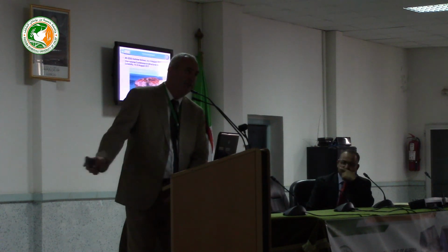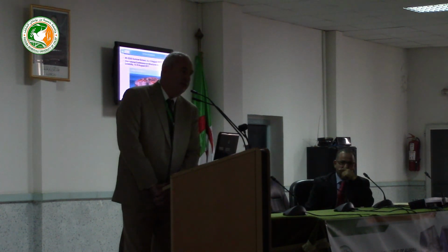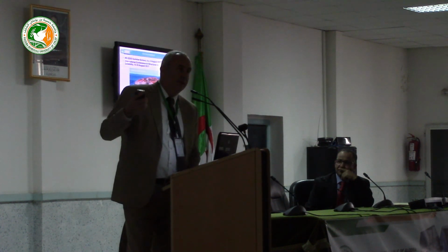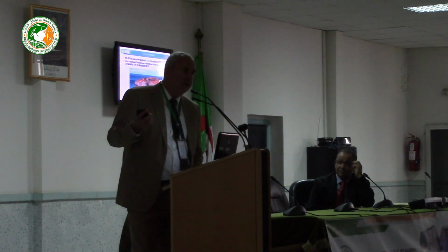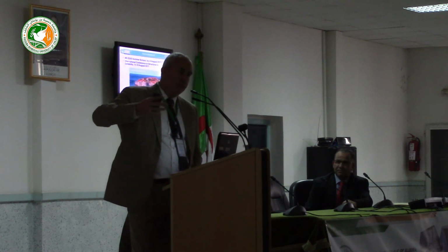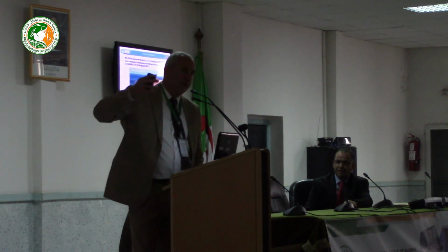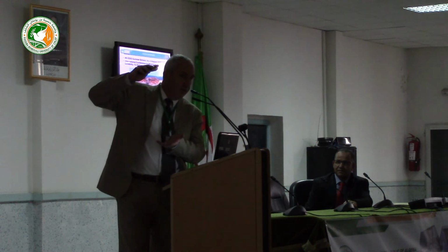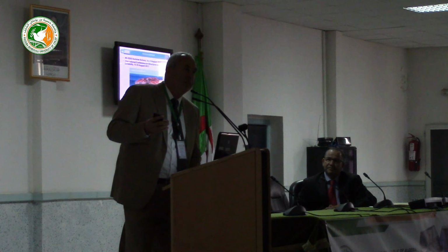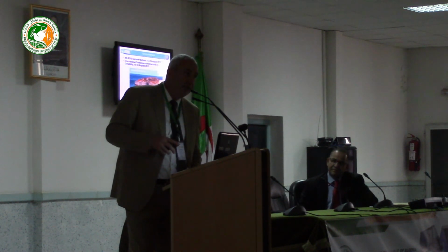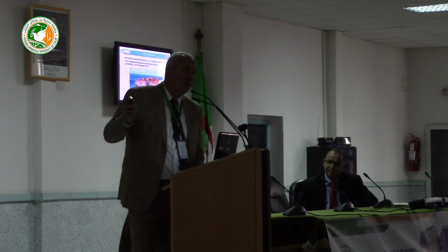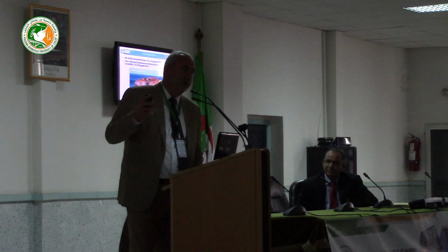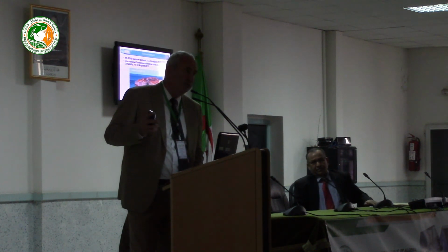And when we speak about elastic plastic fracture mechanics, there is also another work where, for the fracture specimen, we compared analytical solutions with numerical. The analytical solution provides limited results because it cannot take into account the nonlinear behavior when we have load drop. So it helped us to calibrate our models, and we use this model later. So more or less we trust our models when we speak about the J and CTOD which we calculated.